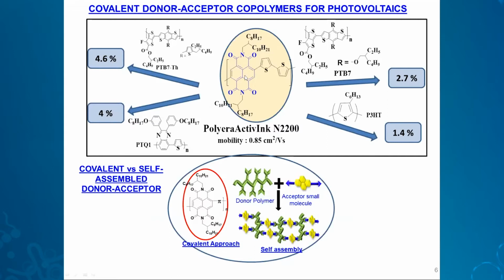And among all the acceptor type materials or the n-type polymeric semiconductors, the polymers based on this unit, the naphthalene diimide or naphthalene diamide, and its higher analog, the perylene diimide, are very promising because they have high electron affinity, good absorption, and good thermal and photostability. So these are some plus points of these systems. And this particular polymer shown here is labeled N2200, the Polyera ActivInk. This was designed and developed by Facchetti, and now it is a commercially available polymer.